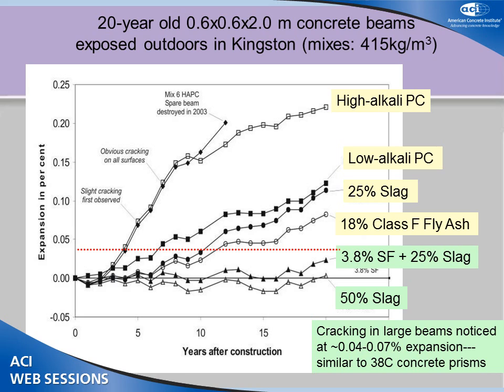So you see the low-alkali cement was next, and then the 25% slag, and then the 18% ash. And the only two that have not expanded over 20 years are the 50% slag and the ternary mix with silica fume and slag. So it mimics the concrete prism.